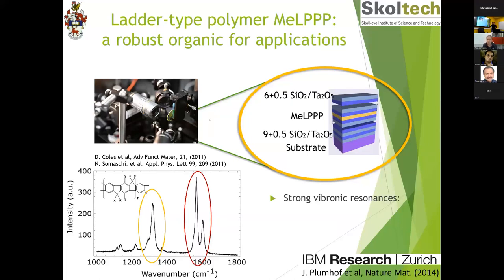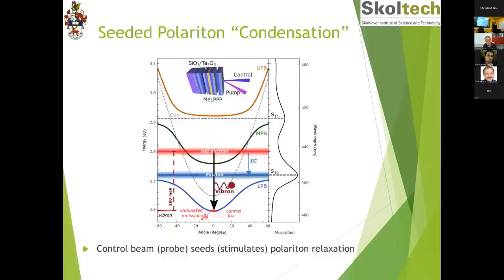And you can see here in Raman spectra that the vibronic resonances can carry really 164 meV for one vibron, 200 meV for another vibron in this structure. So we thought that maybe we can actually use these vibrons in the same way that we used LO phonons in inorganic microcavities back in 2010 in order to accelerate the relaxation of polaritons from the external reservoir to the ground polariton state. And this is what we set out to do here.